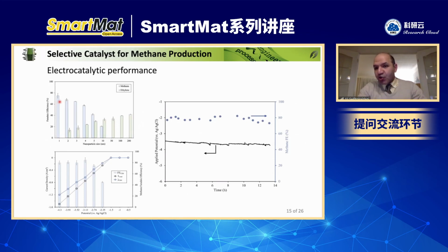I hope I answered your question, but again, this is only one angle to the problem. There might be a lot of reasons, like low coordination, or the shape, or, as Professor Zhicheng mentioned, not having enough surface coverage of CO because it's a very small particle. You don't have so many CO there to even let them couple. So these can be the reasons for not producing ethylene at very small particle size.